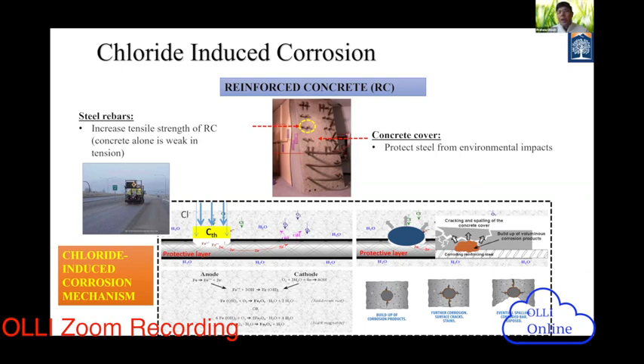So what kind of rebar are we using? We can use epoxy coated rebar, the green epoxy coated rebar. Some of you probably have seen it in your life. Galvanized rebar, with galvanized coatings, and then some composite steel like MMFX. Those are the newest rebars, generally used by DOTs and the Federal Highway Administration to better protect the rebars from corrosion. In that way, the threshold amount will increase, so it will again delay the initiation time. So this is the major process.